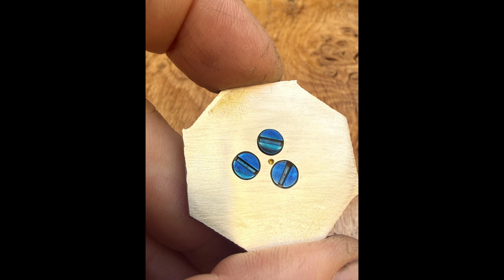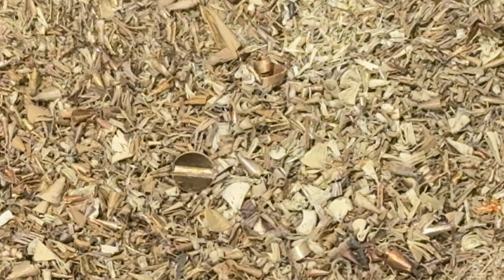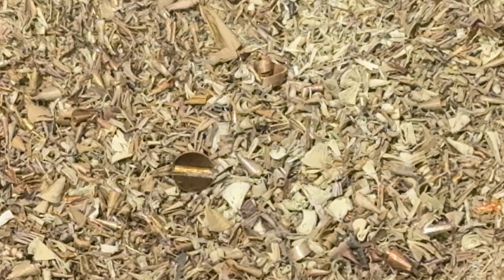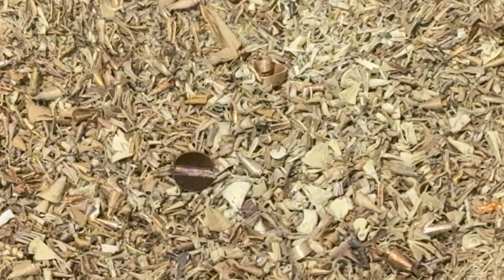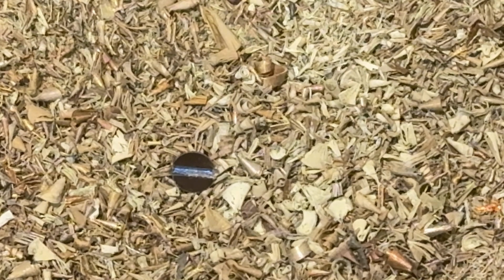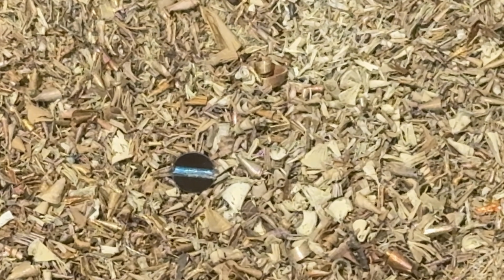Heat bluing occurs when steel is heated to a specific temperature. As the steel is heated, a thin layer of an iron oxide called magnetite is formed. This oxide layer produces a reflected light color, which changes as the thickness of the oxide layer increases. A yellow starts to appear at about 220 degrees centigrade, and blue is reached at about 300. At 320, this blue will start to pale before eventually disappearing.